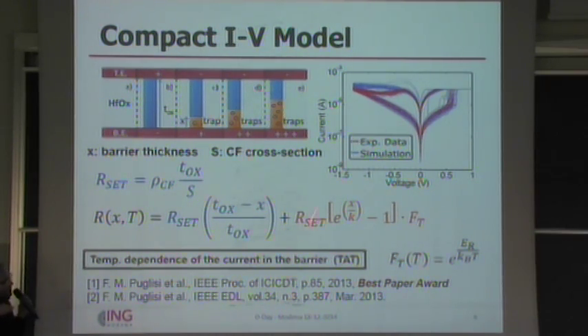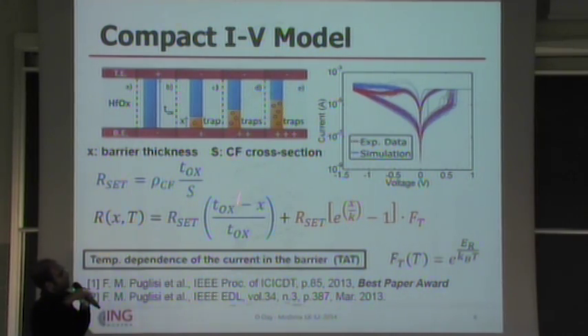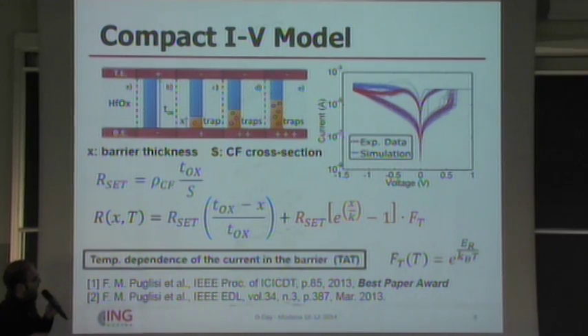And this really completely maps the complex underlying physics, thanks to this K factor here and this temperature factor, which accounts for the temperature dependence of the charge transport across this barrier layer. Then the most important thing about this model is that you don't have to really understand what's written here. The most important thing is that with a very simple model, we can map the electrical response of this device to the physical characteristics of the filament within the structure.